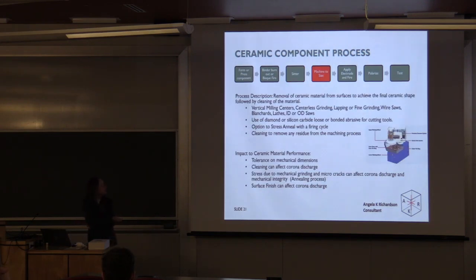In the next step, we're just going to do some machining process. Like any ceramic, you typically are using silicon carbide, diamond-based bonded media, and you can use any normal machining centers. They can be lappers, lathes, etc. And then oftentimes you will stress anneal that configuration because you've broken up that surface.